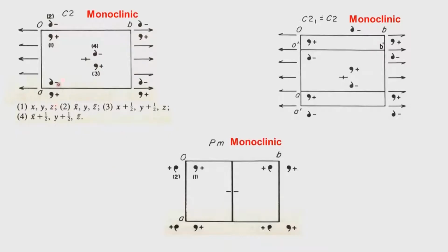And therefore, you have this equivalent point which is x, y, z. The x plus half, y plus half, z is an equivalent point that is generated by the lattice symmetry. This is not an equivalent point which is generated by the symmetry operation. So, the additional symmetry which we have got from the centering should also see the symmetry operation in order to be consistent with the definition of the space group. We have to have the closure property, and therefore, this point number 3 will also see the two-fold axis, which is now generated automatically at half position. Because we have a two-fold at 0, we have a two-fold at half position, we will generate another two-fold. So, this two-fold will take the object 3 onto object 4.